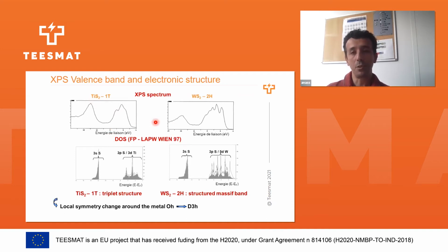By doing some ab initio calculation on the model structures, TiS2 or WS2, we can produce 3 peaks, which correspond to the 3 signatures that we have in the valence band. When we simulate the tungsten disulfide, we have several peaks, which can help to interpret those different peaks in the valence band. So here we can see that the valence band can also be a source of information, but it needs advanced methodology to interpret this data.